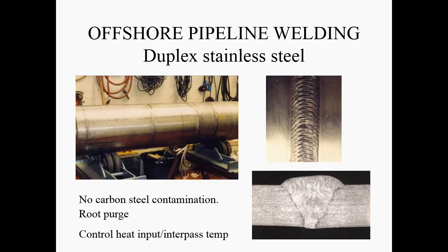Okay. So with all CRA materials, corrosion resistant alloys, welding is a lot more difficult than welding the API grades. And one thing that with duplex stainless steels you need to be very careful is contamination by carbon steel. Why is this? If the duplex stainless steel comes into contact with anything that's carbon steel, any of the API grades, a galvanic cell will form, and the anti-corrosion properties of the duplex stainless steel will be lost.